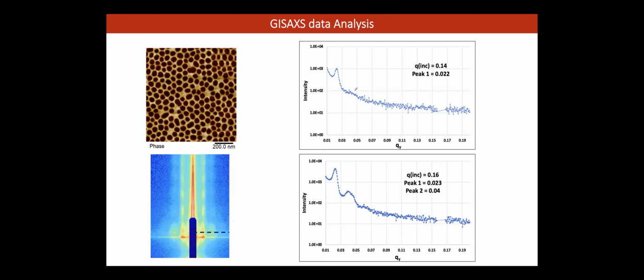And that's because the higher order correlations are wiped out. You look at the AFM picture, and indeed, you can see that the cylinders themselves, in terms of shape, size, orientation, all seem to be scattered all over the place. But interestingly, if you go to 0.16 degrees, then you find that you can see a significant second order peak, and the first order peak did not change much from 0.14. So the average diameter inside is roughly what you see on the surface, and you learn a lot because now you see a second order peak, which means that there are high order correlations.